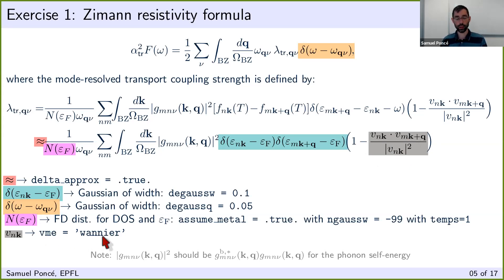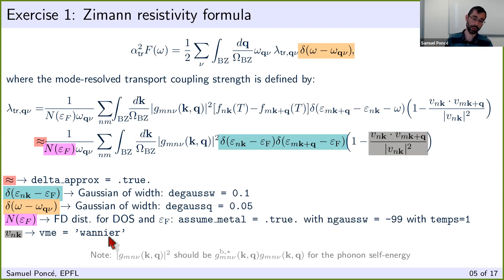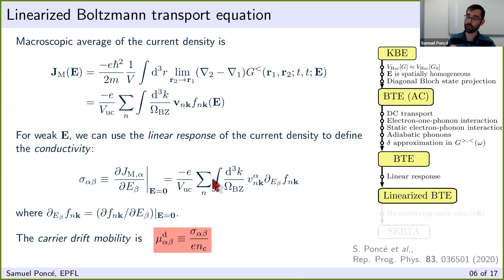For the velocity, setting vme = 'wannier' (previously vme = true) computes it using the Wannier approach. There is now another way called vme = 'dipole', which uses the dipole and the non-local part of the potential and the position operator — this was mentioned during the lecture. In this exercise we'll use 'wannier', but you can try 'dipole' and verify that at convergence both give the same result.